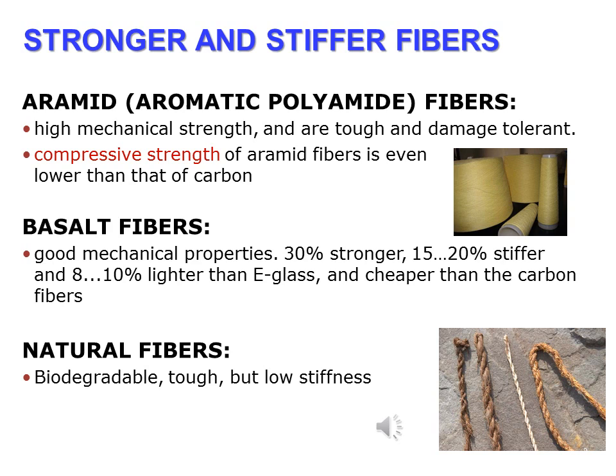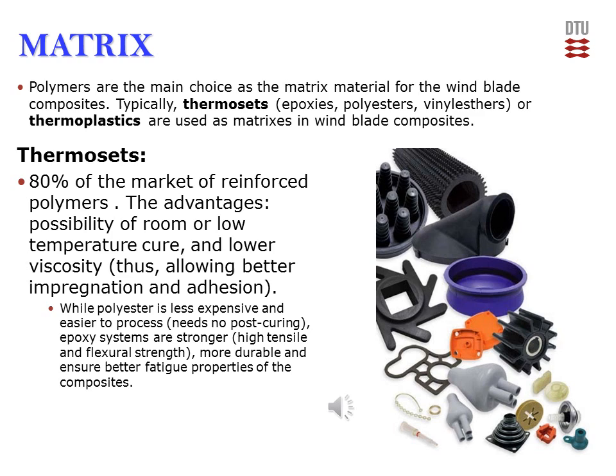Further alternative options of non-glass high-strength fibers include aramid and basalt fibers. Aramid fibers have high mechanical strength and are tough and damage tolerant. However, their compressive strength is even lower than that of carbon. Aramid fibers were introduced by DuPont under the trade name Kevlar. Aramid fibers absorb moisture, can degrade under ultraviolet radiation, and have relatively low adhesion to polymer resins. Basalt fibers represent an interesting alternative to glass fibers — they are 30% stronger, 15–20% stiffer, and 8–10% lighter than E-glass, and cheaper than carbon fibers.